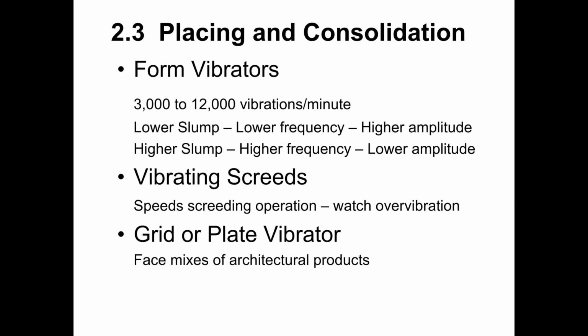You definitely hear the vibrator running, but until you go up to the form and actually put your hand on the form, you don't even know that it's moving. You have to kind of feel the movement because it's such a low amplitude movement. So that's an example of a high frequency, low amplitude vibration, which would be more common today because we're more commonly using higher slump mixes today.